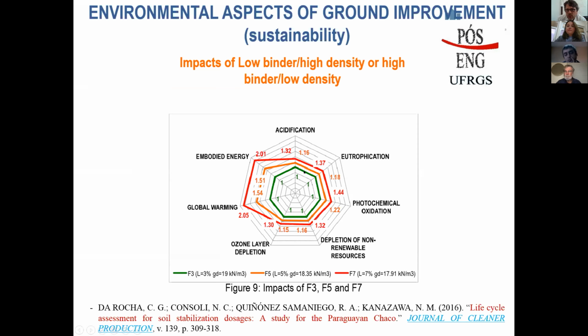And in this case, we have shown that this green one has the same confined compressive strength of the material as the one in red here. The only difference is that in this case, we have used a small amount of lime and a larger density, and in this case here, a higher amount of lime and a smaller density. The density reflects the compaction that you do, and the lime, how much you add.